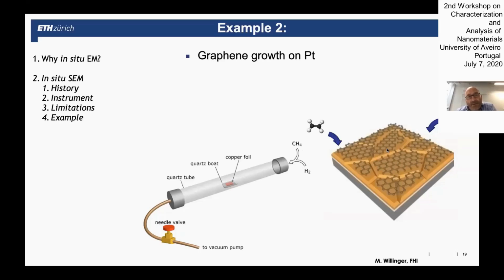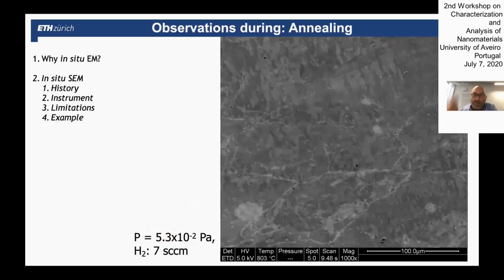At 1000 degrees, the metal surface is so hot that you emit a lot of thermal electrons, so there's a lot of background signal. From all this background signal, I initially didn't believe that we would be able to see the contrast modulation by a monolayer of carbon. But then we did this experiment, and meanwhile we did many.